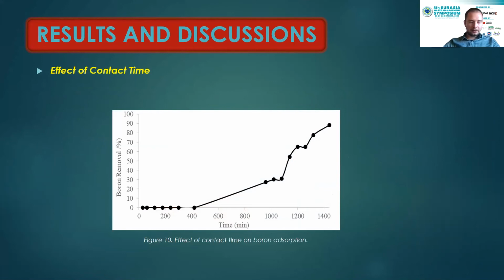Effect of contact time. Inadequate contact time of the boron and adsorbents may not provide good removal. Therefore, optimal contact time was determined. For this purpose, geothermal fluid at pH of 4 was shaken with 2.5 gram fly ash at 25 Celsius for different periods. The results were given in figure 10. As can be seen in this figure, the boron removal was not determined until the 400 minutes. Boron removal increased gradually after this period, and 88 percent boron removal was obtained in 24 hours.